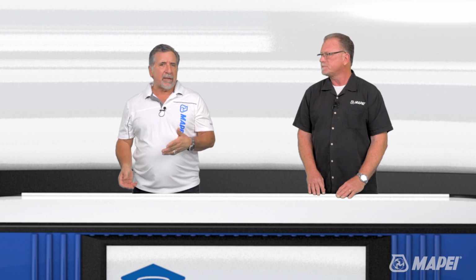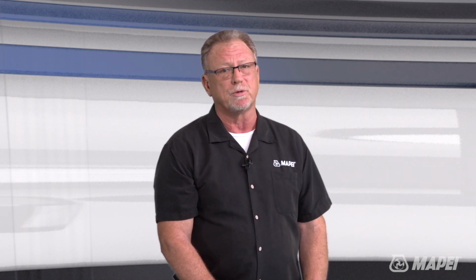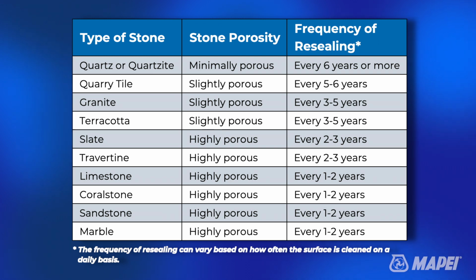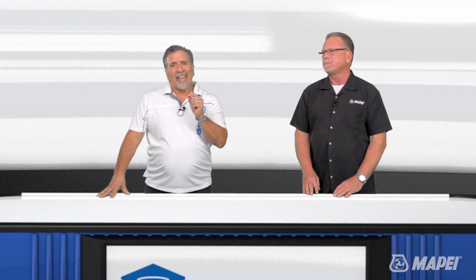How often should we be applying sealer? Each application can be a little different. It's important to periodically run a porosity test to see if the surface absorbs by sprinkling some water on a few small areas. If the water easily absorbs, it's time to reseal. The frequency of resealing is directly related to the porosity of the stone, how it's being used, location, and even the maintenance. As the chart on the screen shows, it can range from every year for more porous stone to up to every 5 to 6 years for dense stone. Okay, thanks, Nick. That's great advice.